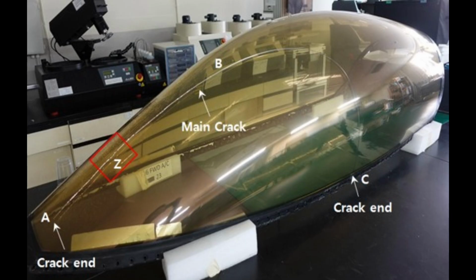As aircraft fleets aged, the invisible degradation accelerated. Crack growth followed Paris law with brutal consistency. Growth rate increased exponentially as cracks lengthened. What had taken years to initiate now required only months to become critical. Aircraft that survived early service entered a danger zone where failure probability rose sharply. Maintenance schedules, designed around visible wear, offered no protection against microscopic fracture.